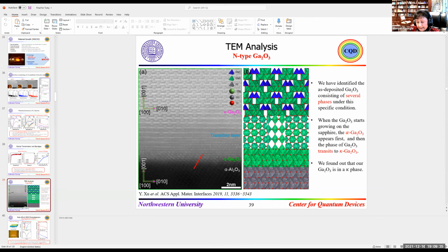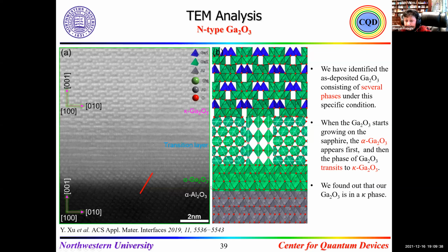If I go again to here, this is what you were asking about exactly. It's a very nice analysis because for that you have to be an expert - the person, the group that did this, were great scientists, material scientists, because as you can see beautifully, you go step by step and can see the change of phase. Why? Because in general for epitaxy, everything you do takes exactly the symmetry of the substrate. You go up - so here, alpha aluminum oxide immediately becomes alpha gallium oxide, and after that goes to kappa. That is the transition step by step, as you can see.